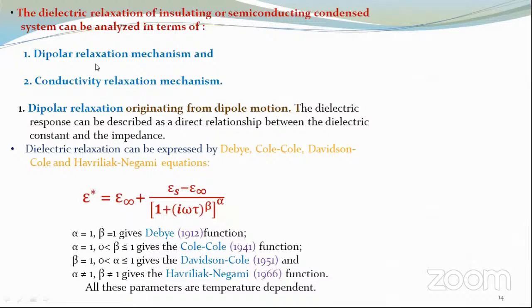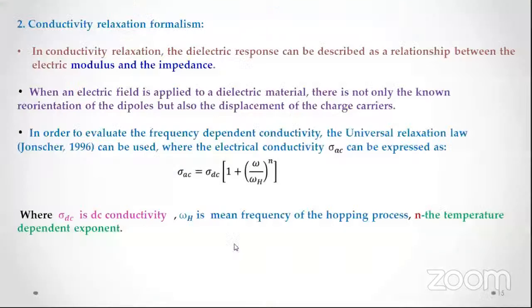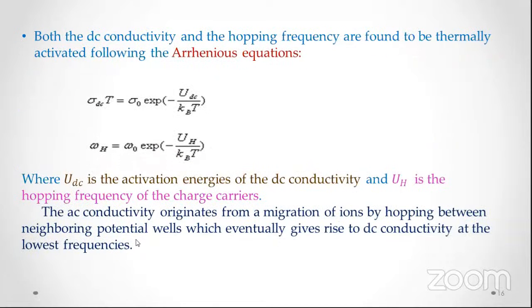So there are two types of relaxation here: the dipolar relaxation mechanism and the conductivity relaxation mechanism. The dipolar relaxation mechanism can be studied using formulas given by Debye, Cole-Cole, Cole-Davidson, and Havriliak-Negami equations. Using these various models, we can study the dielectric properties of the said materials. In the case of conductivity relaxation, we have used Jonscher's formula. In this case, AC and DC conductivity are connected in this way. So we can study the conductivity relaxation using Jonscher's formula, and we can know the activation energy of our charge carriers. We have used these formulas.